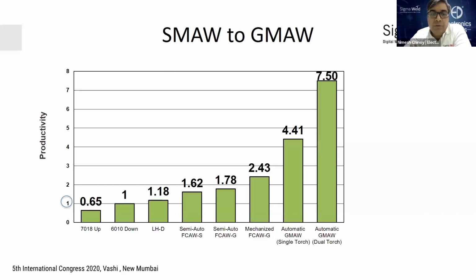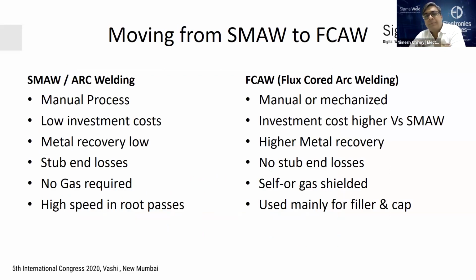So that's the progression depending on the job, depending on the level of automation you want to use. You can easily go from 600 grams to at least a semi-automatic flux core welding of about 2 kgs an hour, or a mechanized trolley to take it up to 2.5 kgs an hour. When you move from arc to flux core, you need to keep in mind that you're moving from a manual process to a mechanized process. Your investment cost will be slightly higher compared to arc welding. Your metal recovery will be very high. That means per kg that you pay, you will have more deposits, no stub losses.